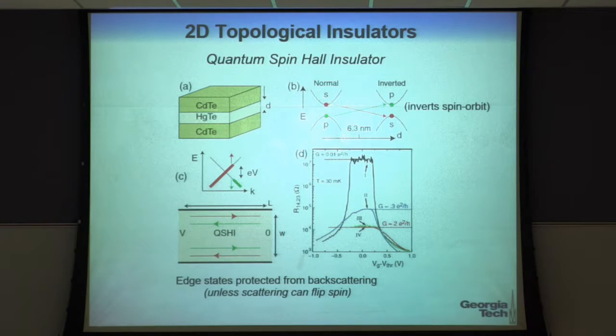So this is a quantum well. And if you make the quantum well thin enough, then what happens is that the hole states and the electron states, the discrete hole and electron states confined in the quantum well, actually invert. So the hole states go above the electron states, like so. And that inversion has to be undone when you get to the edges. And so undoing that gives you, again, an edge state, which is in fact a topological edge state.